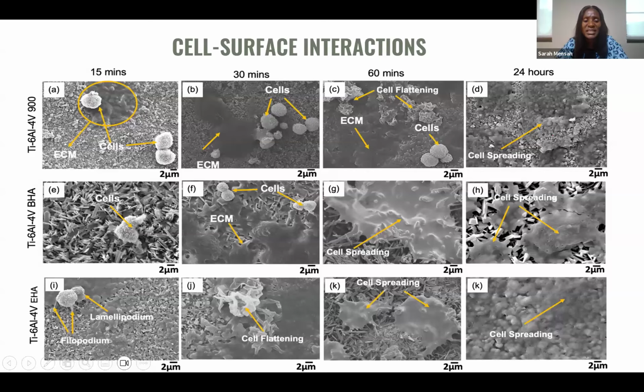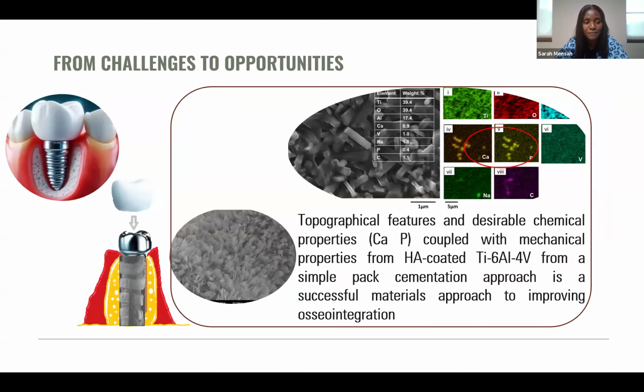So with this, we could see that indeed we have been able to take a biomaterial from just being bio-inert to being bioactive by coating methods and being able to characterize them to see the properties that we come by. So we could see that from challenges, we are able to have opportunities to work with materials and take them to the different phases and functionalities that are desirable. When you look at this image, a titanium metal that is bio-inert, based on our coating method, we are able to introduce this roughness onto them, whereby we have these nanorods that help the material to function very well as an implant material, thereby reducing the chances of failure.